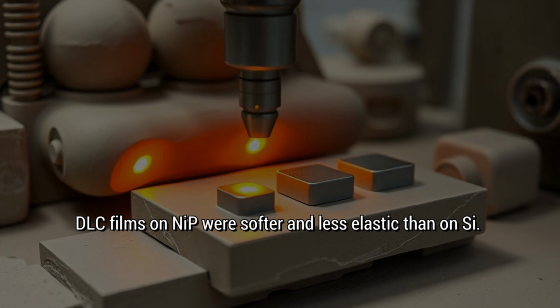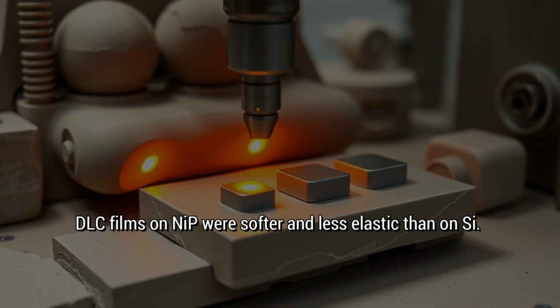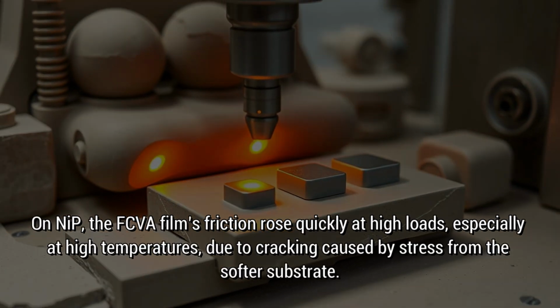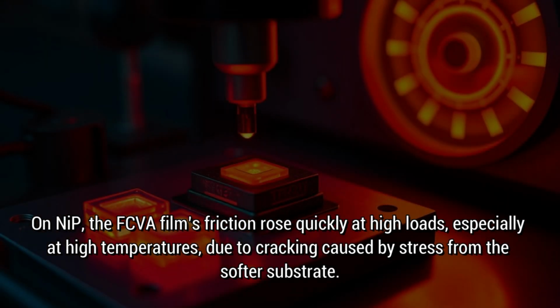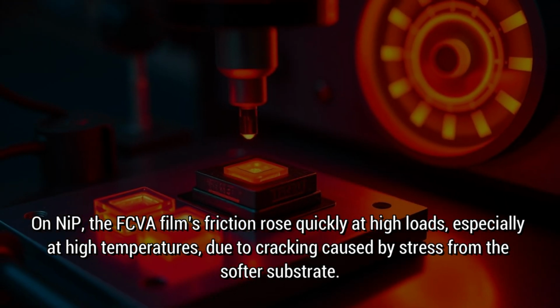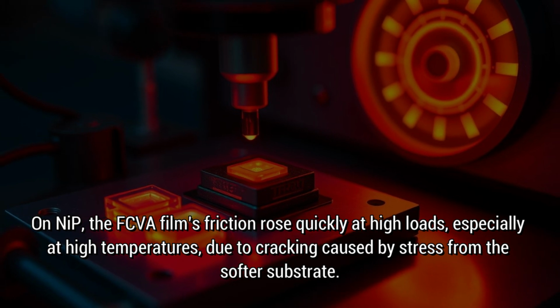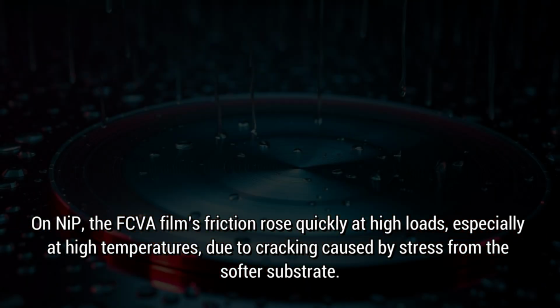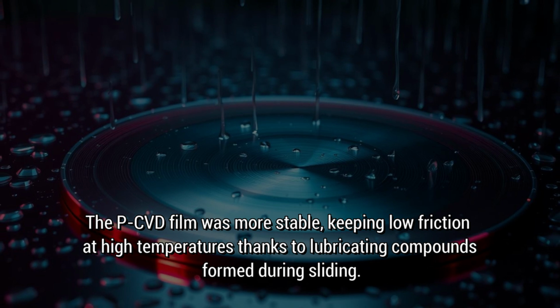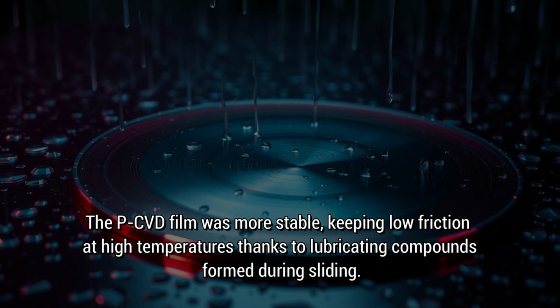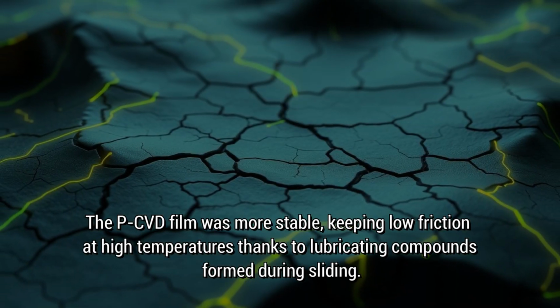DLC films on NiP were softer and less elastic than on Si. On NiP, the FCVA film's friction rose quickly at high loads, especially at high temperatures, due to cracking caused by stress from the softer substrate. The P-CVD film was more stable, keeping low friction at high temperatures thanks to lubricating compounds formed during sliding.